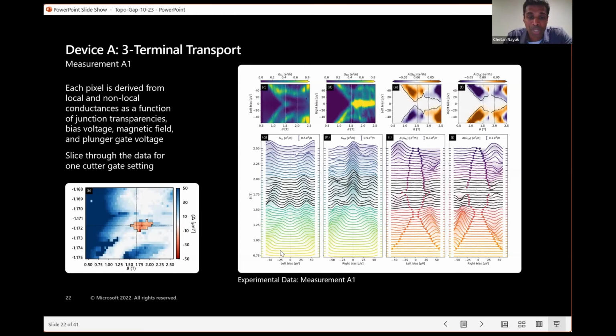Here's another way of representing the same data, representing the four conductances as a function of magnetic field and bias voltage. You can see zero bias peaks appearing here and here that are stable, and the gap closing and reopening like this. This is one slice through the data for one cutter gate setting, but actually every pixel here is derived from both the local and non-local conductances as a function of junction transparencies, bias voltage, magnetic field, and plunger gate voltage.